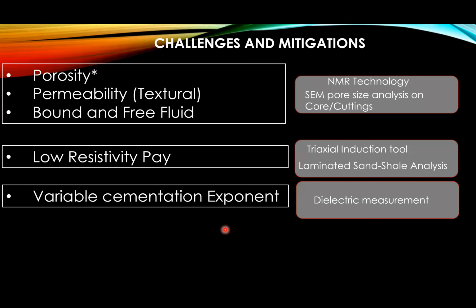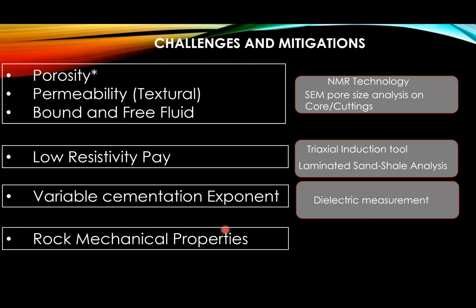But dielectric here, the water saturation will give us an invaded zone water saturation, because these pore sizes are a little bit bigger than in the unconventional, organic-rich shales. So ideally, you would expect some kind of invasion within the near wellbore. So dielectric water volume will actually be reflecting the filtrate going into that near wellbore area. But with a near wellbore saturation, the Sxo kind of measurement, we can derive a variable m. That variable m we can then fit into our saturation-based model to give us a good hydrocarbon saturation estimate.